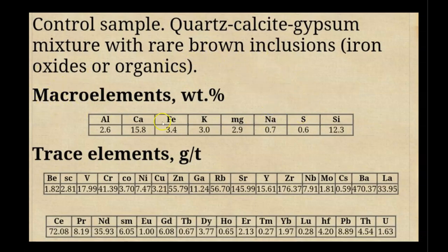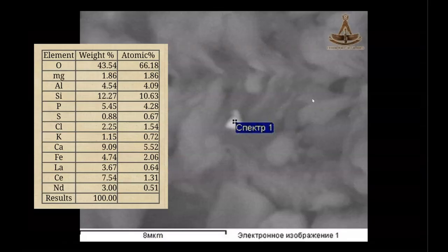in the macro analysis, which has the carbon and oxygen removed, leaving very small percentages of aluminum 2.6%, calcium 15.8%, iron 3.4%, potassium 3%, magnesium 2.9%, sodium 0.7%, sulfur 0.6%, and silicon 12.3%. All very normal stuff, and a bunch of trace elements down here, all in too small of concentrations to be relevant at this point. But as always, the control sample is used for comparison, which we will get to at the end.